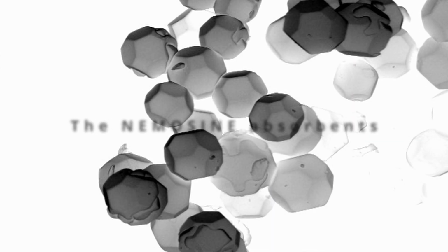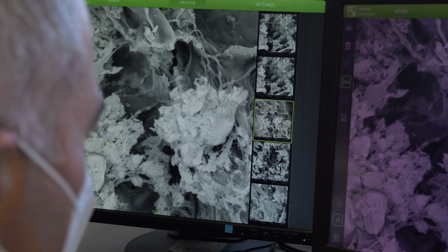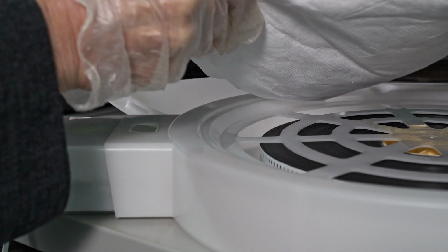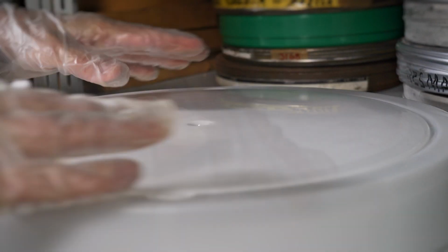The NEMOSINE EU project has developed an acetic acid absorbent based on metal organic frameworks. MOFs can be tailored for the efficient absorption of acetic acid in the presence of humidity, which is the case of cultural heritage based on cellulose derivatives. The research is focused on hydrophobic MOFs that could lead to the control of acetic acid levels inside the boxes. The MOFs found displayed an enhanced selectivity towards this gas in comparison with other absorbers like zeolites and activated carbon. Consequently, MOFs should help the end users to prevent, detect, and avoid the vinegar syndrome degradation.